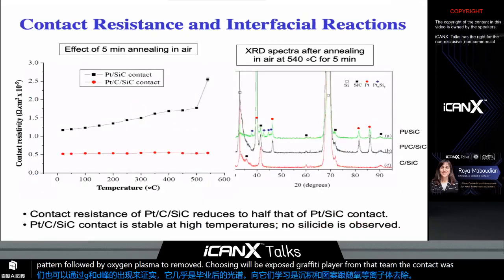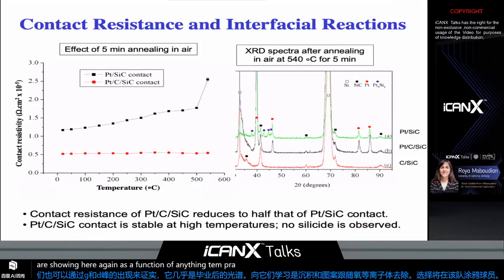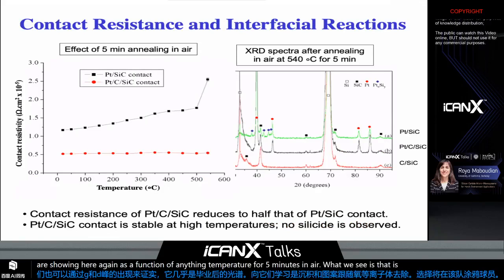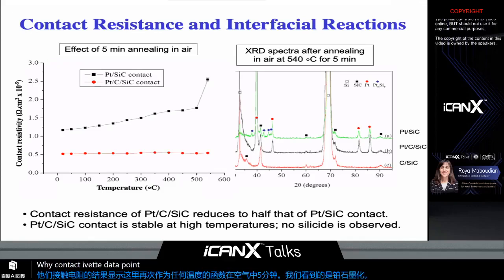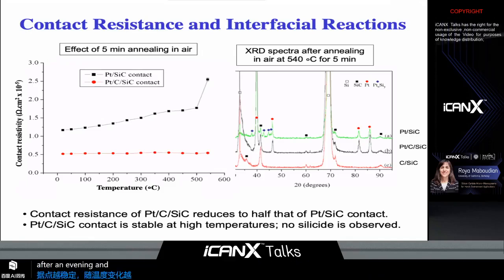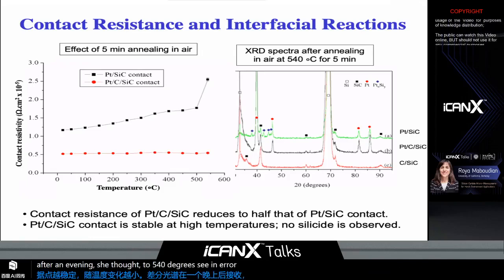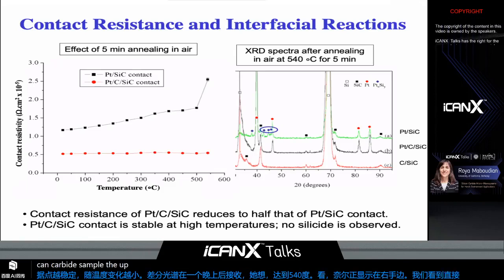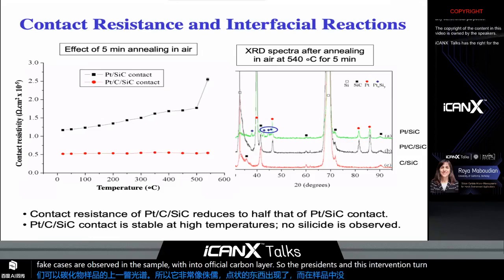The contact resistivity results are shown here again as a function of annealing temperature for 5 minutes in air. What we see is that the platinum graphitized silicon carbide contact, the red data point, is more stable, exhibiting little change with temperature. X-ray diffraction spectra taken after annealing to 540 degrees C in air are shown to the right-hand side. We see that the direct platinum on silicon carbide sample, the upper green spectrum, shows various platinum silicide phases showing up, while no platinum silicide phases are observed in the sample with the interfacial carbon layer. So the presence of this interfacial carbon layer seems very effective at preventing the reaction between platinum and silicon carbide from taking place, resulting in a more thermally stable contact.